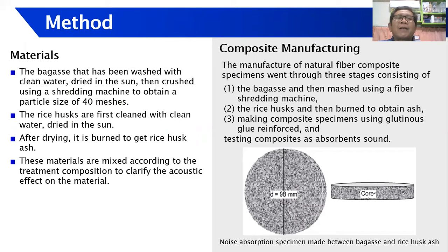The bagasse is washed with clean water and dried in the sun, then crushed using a shredding machine to obtain a size of 40 mesh. The rice husks are first cleaned with clean water and dried in the sun. After drying, they are burned to get rice husk ash. These materials are mixed according to the treatment composition to clarify the acoustic effect on the materials.